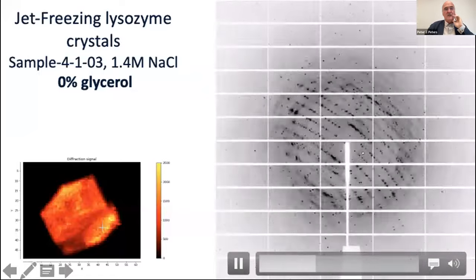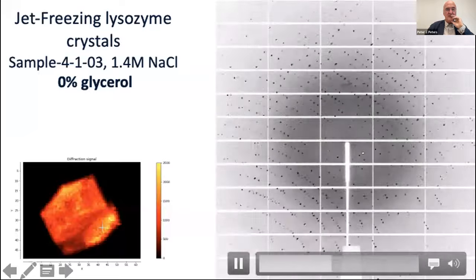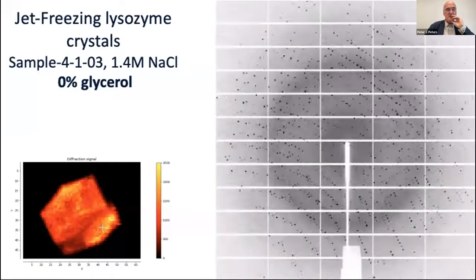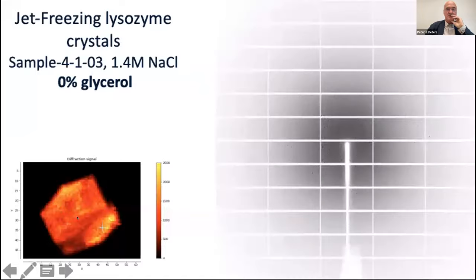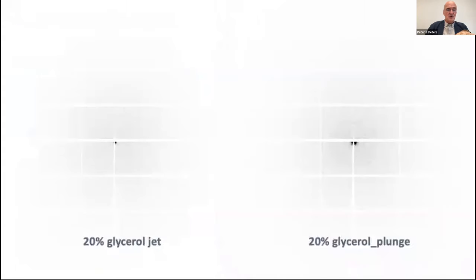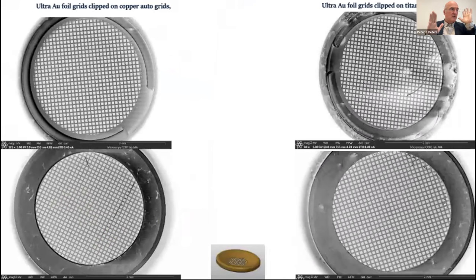And as you can see here, you get the beautiful diffraction pattern that comes with the X-ray results based on the crystal that is formed in this particular protein. So that gave us good information that this can be useful for the X-ray people. And this work that I just showed you is to optimize the system, make the jetting better, try all kinds of conditions to vitrify cells, and then not use the microscope that takes too much time, but use the X-ray. So we send every month, at the moment, 100 samples to Grenoble and do X-ray work overnight, and we get the data back next morning.